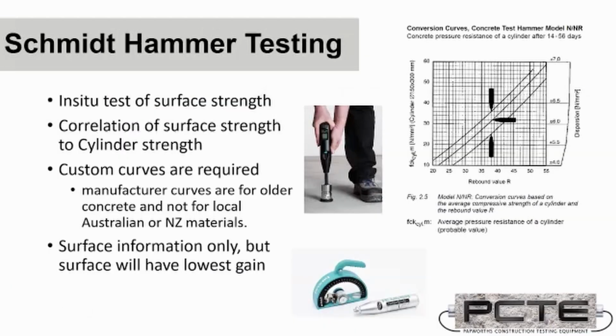So let's start with Schmidt Hammer testing. Schmidt Hammer tests are an in situ test of the surface strength of concrete. So we use the Schmidt Hammer, we strike the surface a number of times, and it records a value that correlates to surface hardness. If we work in the concrete laboratory and we collect the surface hardness values from cylinder samples that are then broken, we can build compressive strength curves like the one on the right-hand side of the screen, which have a relationship between rebound value, R, or for Silver Schmidt models Q, and compressive strength. This relationship is tied to the samples that are broken.